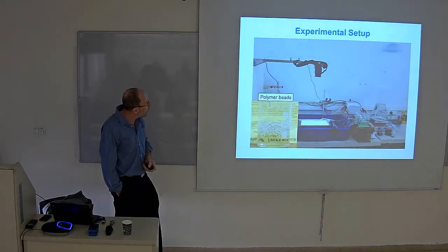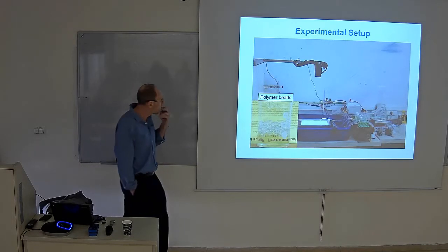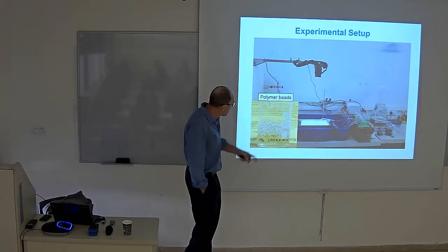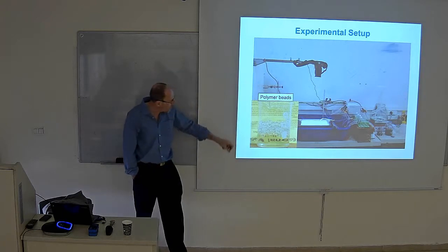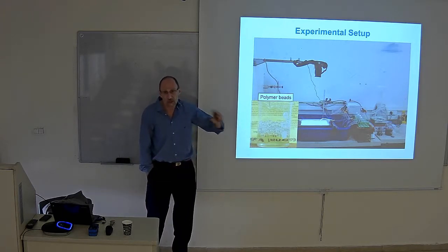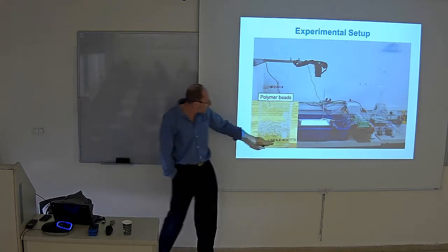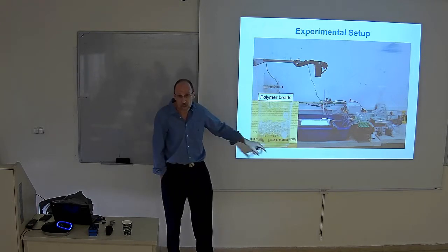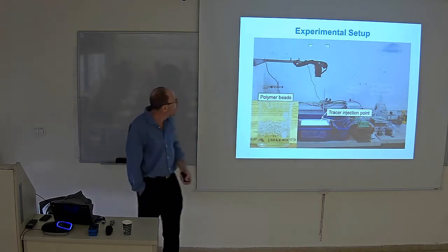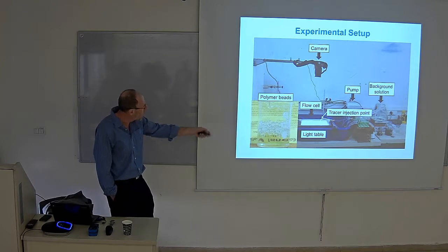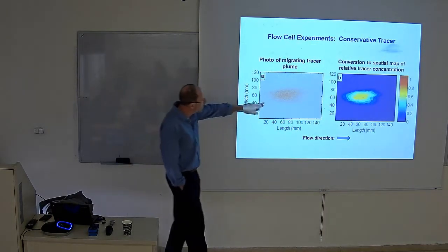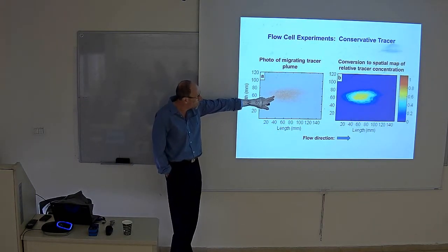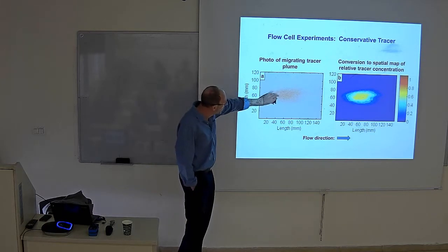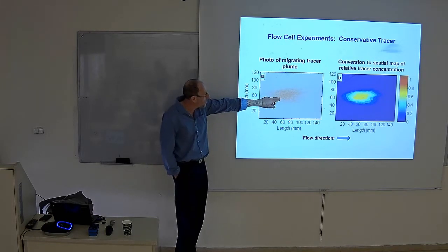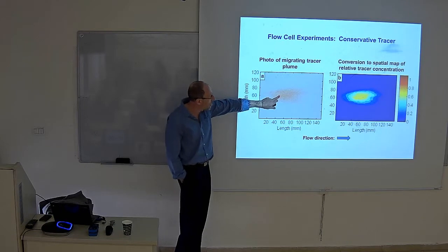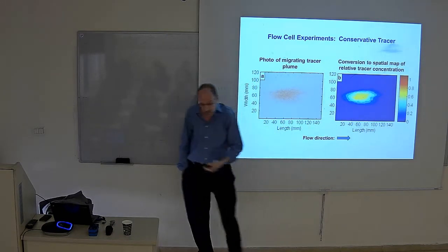And just one other thing I want to show, I mentioned at the beginning we have some geochemical surprises. We developed in the lab these polymer beads where you add water to them, they have the same refraction index. Okay, so you have essentially a transparent porous medium that you can work with. So we did a number of experiments here in the flow cell. We're injecting, this is what it looks like. We inject, in this case, Congo red, but you can inject nanoparticles, use a calibration curve to change the color intensity to concentration, and you get a map of the concentration from there.